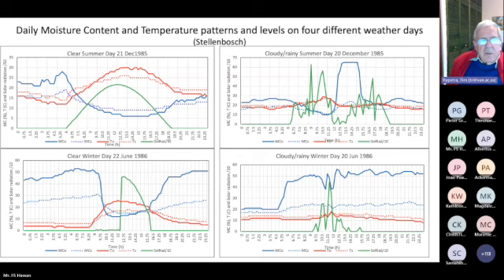So here you can see that the red curve indicates the temperature variation. At sunrise, say at 6 o'clock on the clear summer day, 21st of December, the temperature starts picking up and goes quite high. Actually, it goes higher than the temperature you will find inside the timber with roof protection above it. That difference we refer to as overheating. It's often possible that when objects are dark in color, the overheating can be quite severe, even as high as 60 degrees centigrade contact temperature when you touch wood coated with a black type of paint.